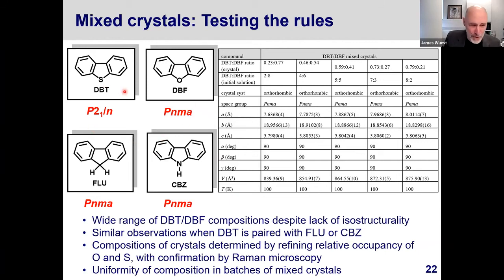This makes the story a little bit more interesting and a little bit richer. We started out this work by attempting to form mixed crystals of the thiophene and the furan, and we succeeded. We characterized a large number of these mixed crystals by single crystal X-ray diffraction, and we found that it was possible to get mixed crystals with continuously variable compositions over a very wide range. If you look at the table here, you can see that we obtained crystals that have the thiophene 23%, furan 77%, up to crystals that contain 80% of the thiophene and 20% of the furan.